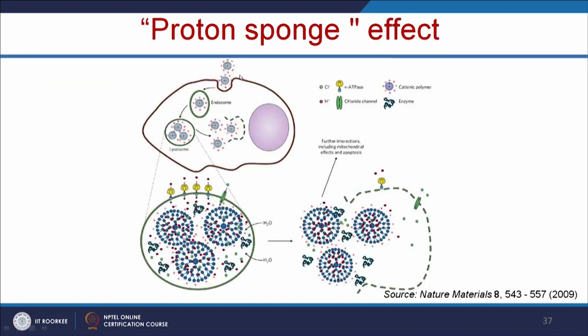The positively charged nanoparticles will attach to the cells and form the endosome. And these endosomes will fuse with the lysosome, and form an endolysosome. And this endolysosome, due to the large amount of positive charge in it, will break and release the nanoparticle into the cytoplasm. And this nanoparticle can release the drug to the nucleus and induce the therapeutic effect. So this is called the proton sponge effect.